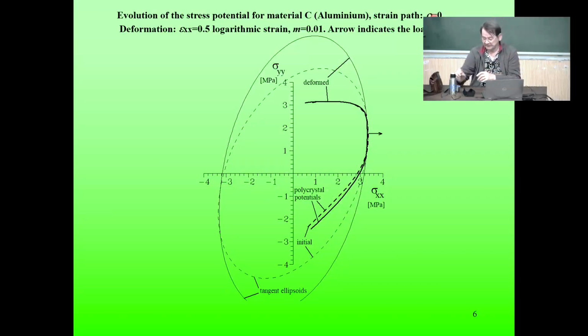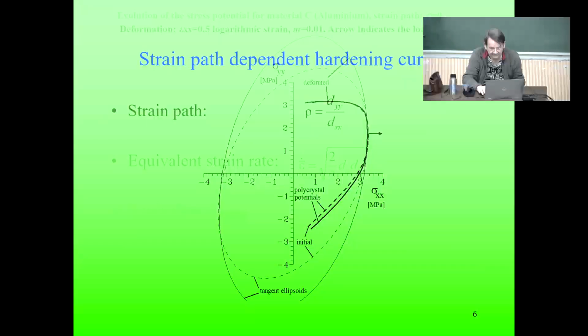The first point is a plane strain point. If you load it that way, then the loading is at this point on the yield surface, and it's not moving basically. That's interesting that here that strain of 0.5 was applied, but it was not moving significantly. And then there is a lot of change in the Hill ellipsoid. It is tangent before and after. It becomes more flat, the yield surface, as we apply the strain in the rho equals 0 position.